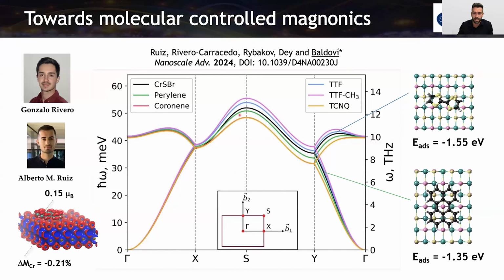All this has an effect in the magnon dispersion, it is affecting the optical magnons, especially here. We can see the TTF and the TTF-CH3 here. This is the main effect compared to the pristine, which is in black. And we are affecting especially this gamma Y direction. So this bond of sulfur is the main thing that we are affecting, and where the charge transfer is, we are modifying these two competing mechanisms that I showed before in the magnon extra intronics work.